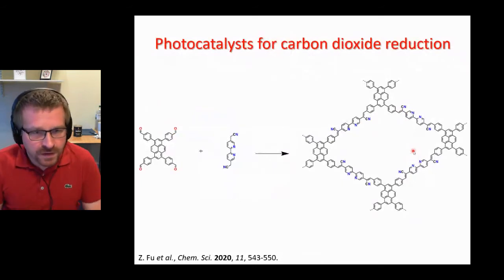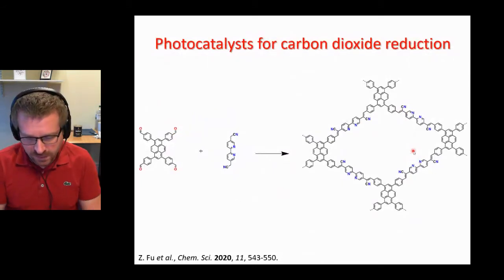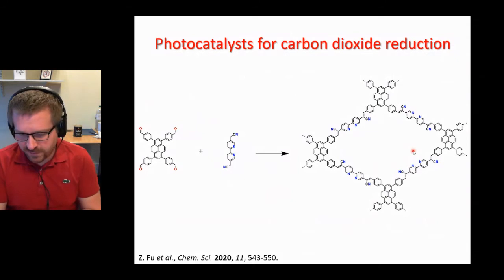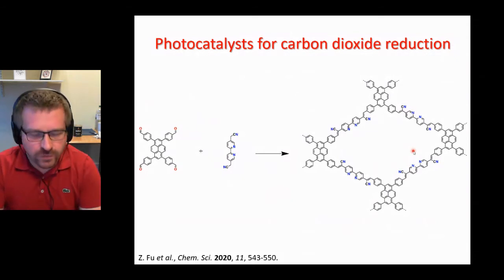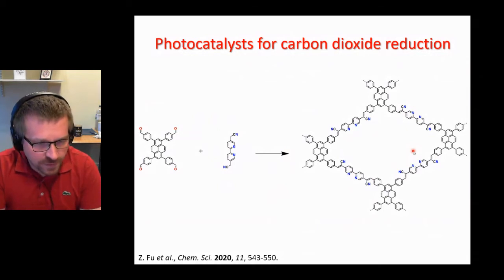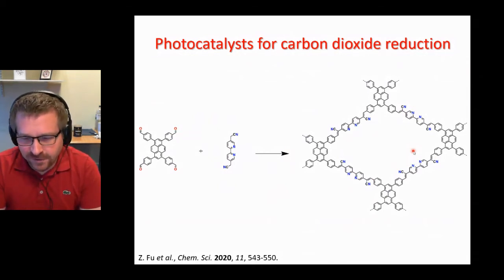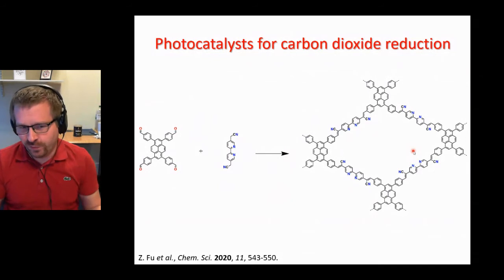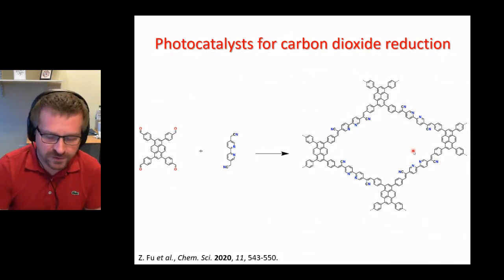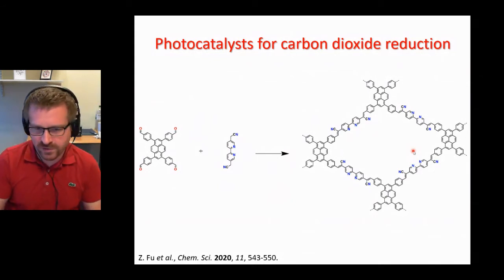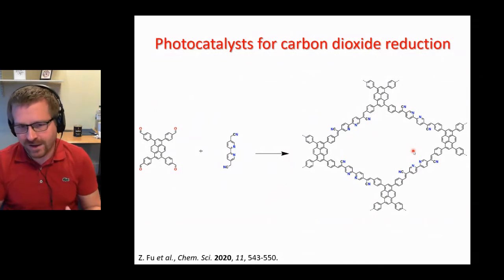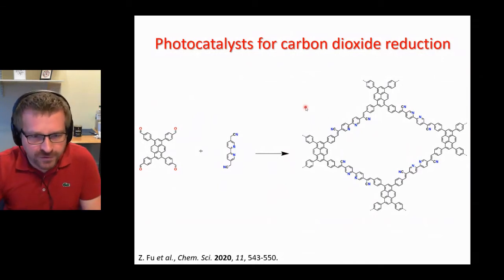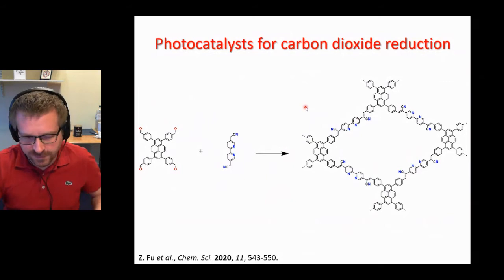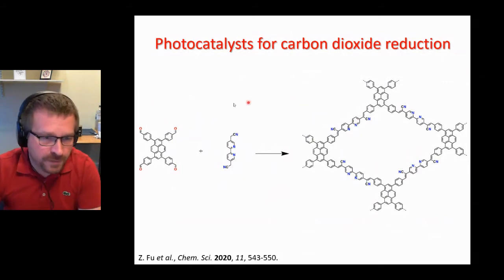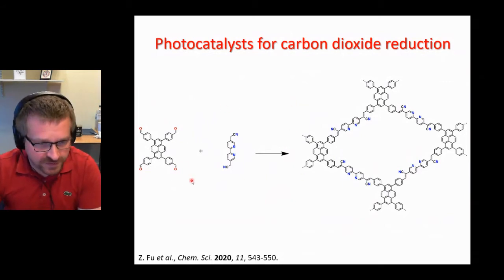And this was really where we started as well, looking at different systems. We started off actually looking at other systems that contained residual palladium in the system, but we found that the selectivity of these systems is really, really poor for CO2 reduction over hydrogen production. And that's why we changed tack a bit, looking at other reactions to make more selective systems that avoid having palladium present in them. And this is one of these examples.